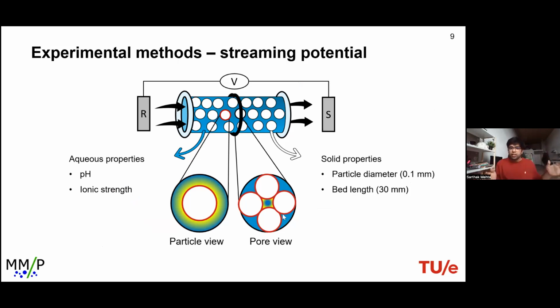As we pass an aqueous media through this packed bed of silica particles, a potential is generated across the bed. This potential is because of the ions stripped off from the diffusive region, creating a net potential that is measured using the open circuit voltage and a voltmeter.